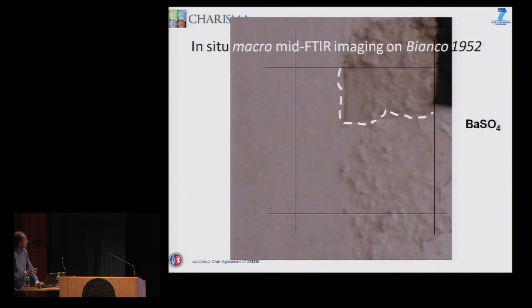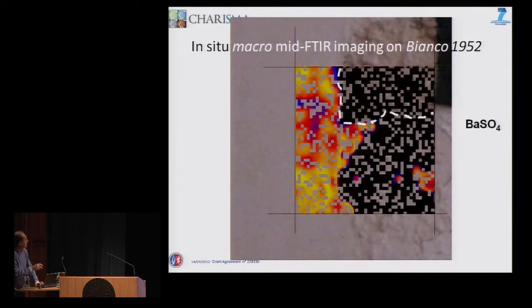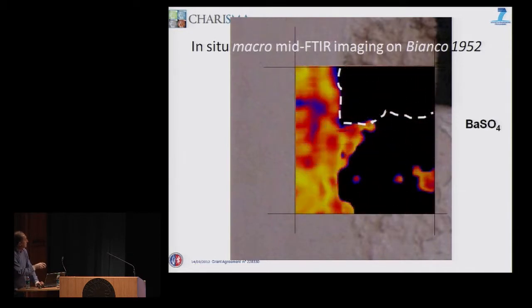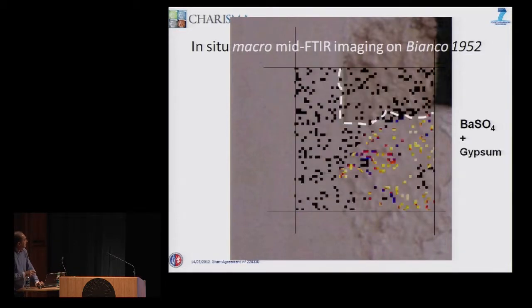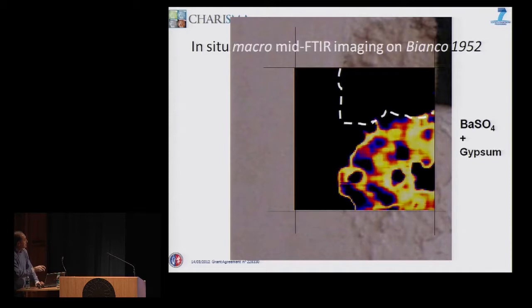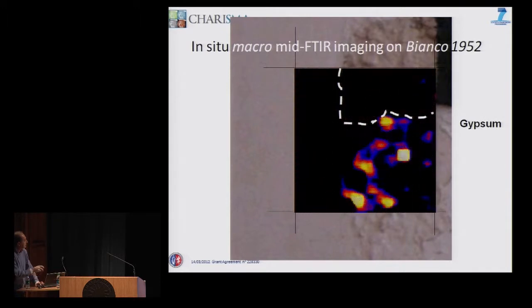And barium sulfate was detected in this part. No barium sulfate was detected here, but barium sulfate plus gypsum was detected in this part. And in these black points here, gypsum alone was detected. So we learned from this examination that the bumps, the rugosity, were made of gypsum.